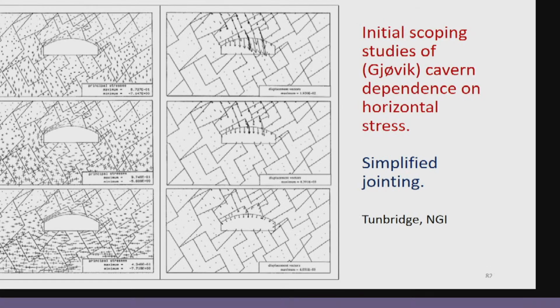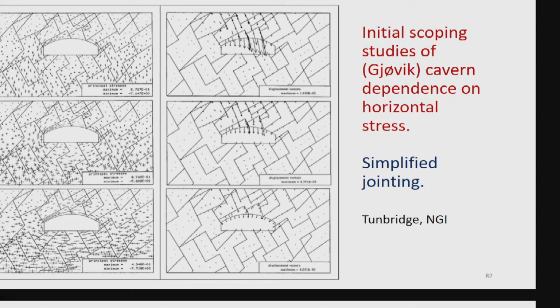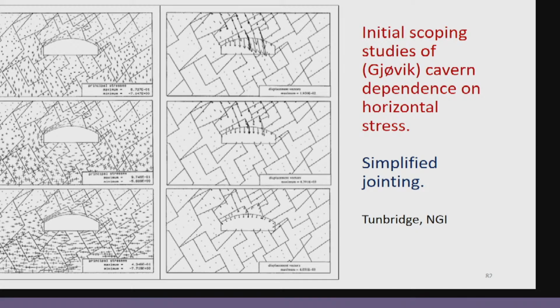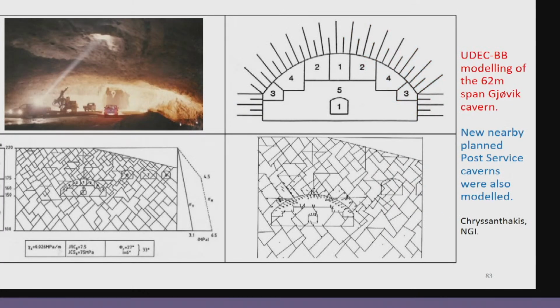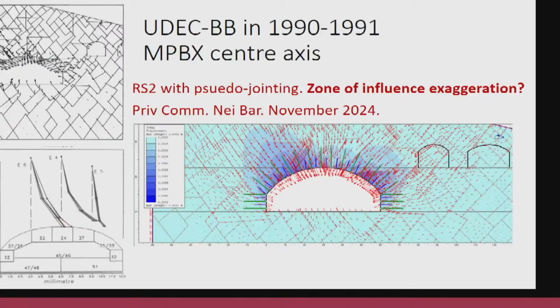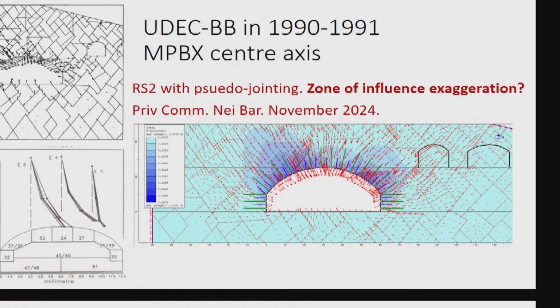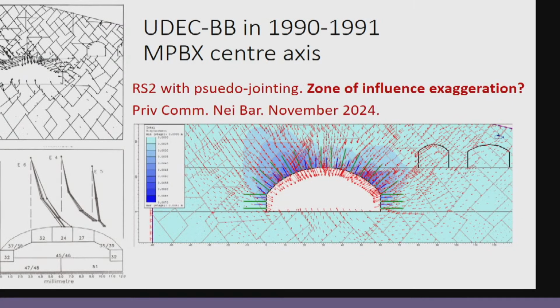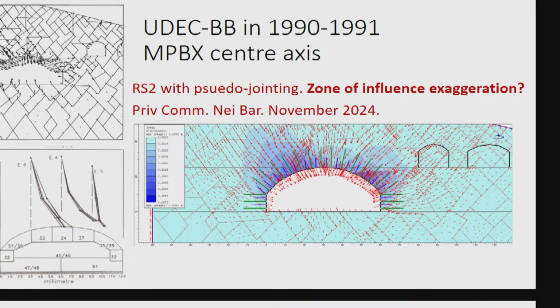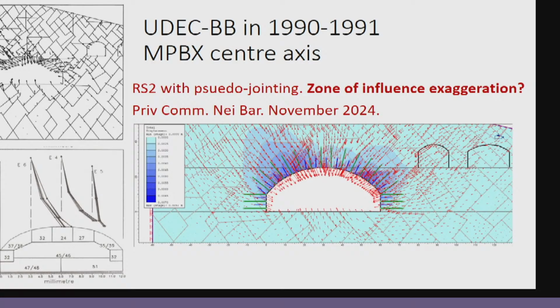Early UDEC studies: low horizontal stress, intermediate horizontal stress, high horizontal stress. The reality was somewhere in the middle between 2 and 3. So you see the first stage of excavation, the top heading on the right there from UDEC BB. And then you see top left, one of the big caverns has been excavated, and it had some effect. So now the deformation is like 7 or 8 millimeter, and it's very close to what the MPBX show.